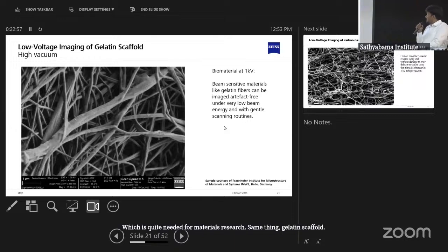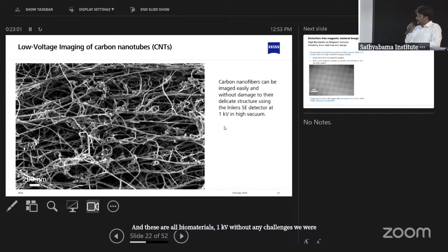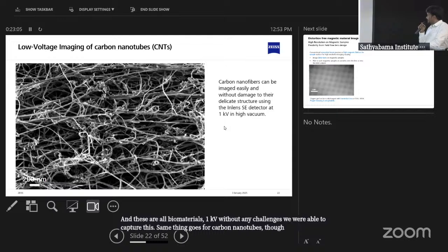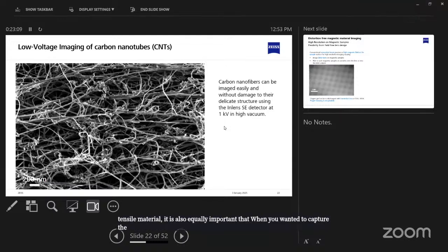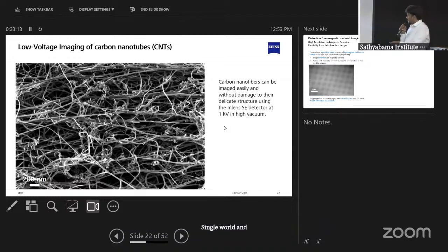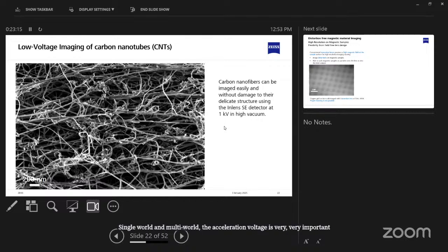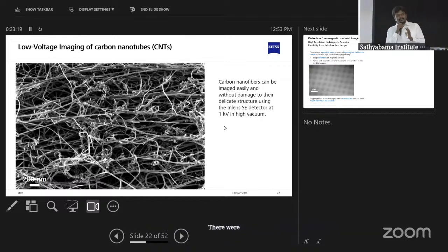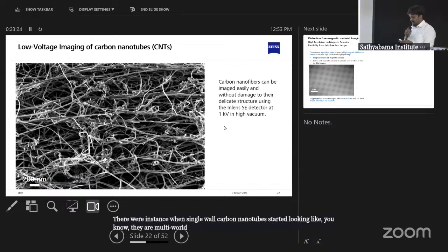And these are all biomaterials, 1 kV. Without any challenges, we were able to capture this. Same thing goes for carbon nanotubes. Though they are high tensile material, it is also equally important that when you want to capture the surface morphology, thickness measurement, differentiating between single-walled and multi-walled, the acceleration voltage is very, very important. If you start playing around with your acceleration voltage, there were instances when single-wall carbon nanotubes started looking like they're multi-walled because of the ghost imaging. So that's also quite important.